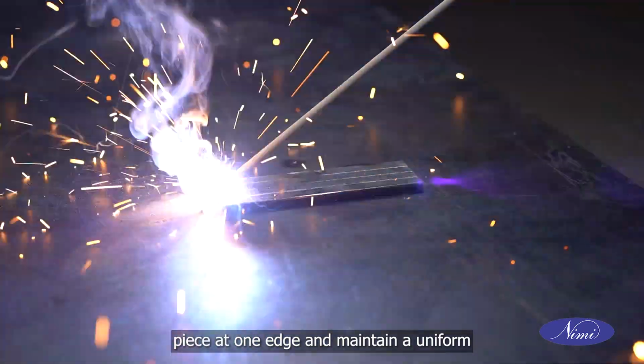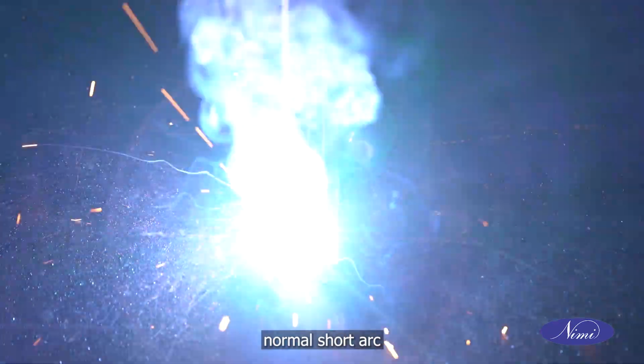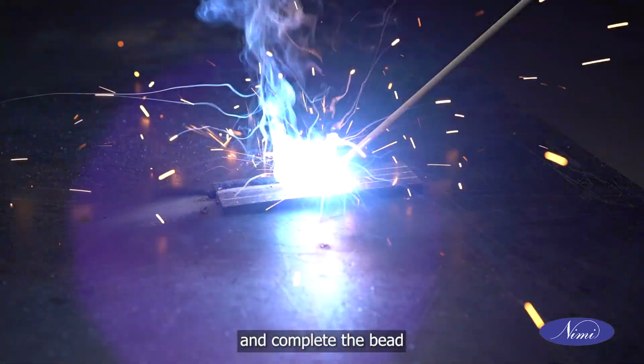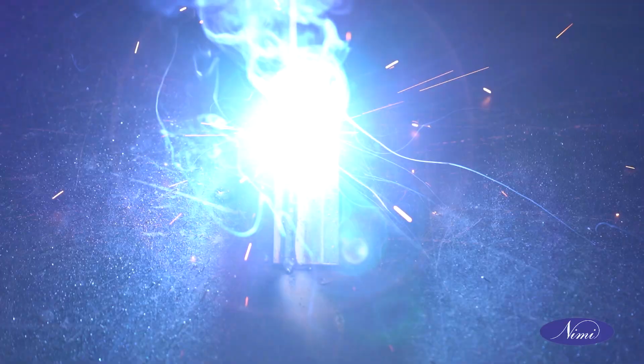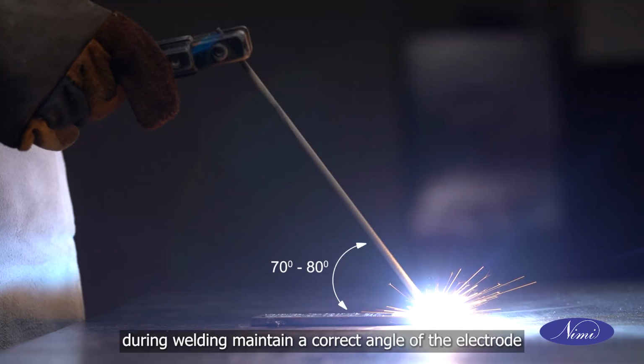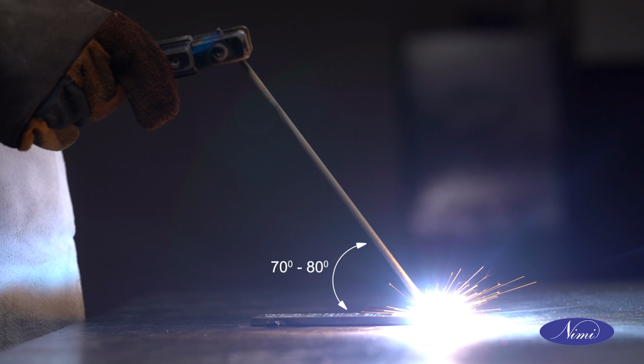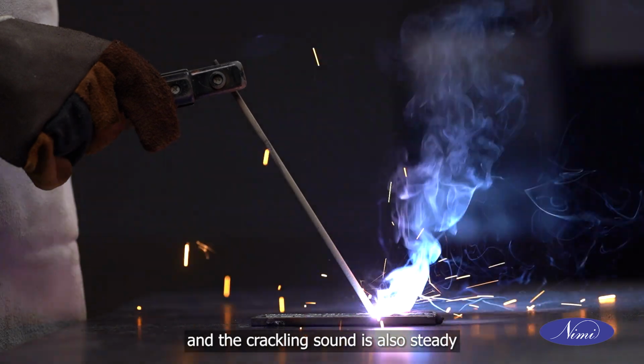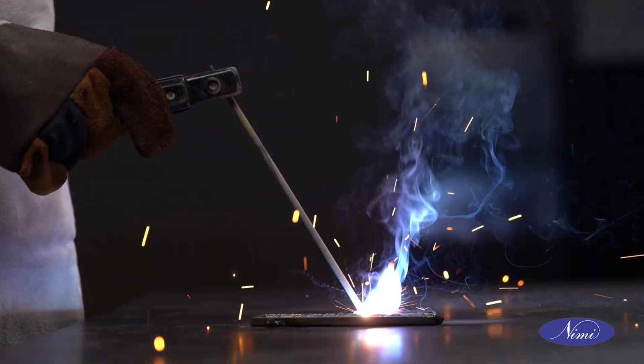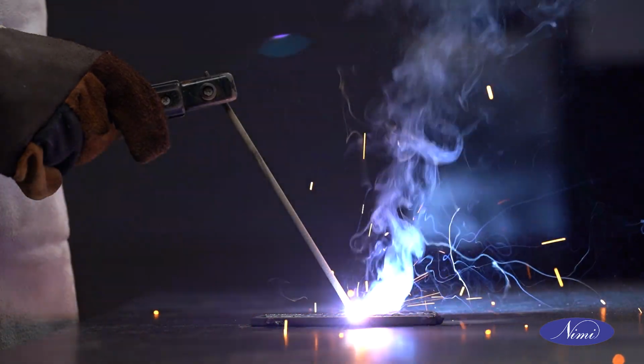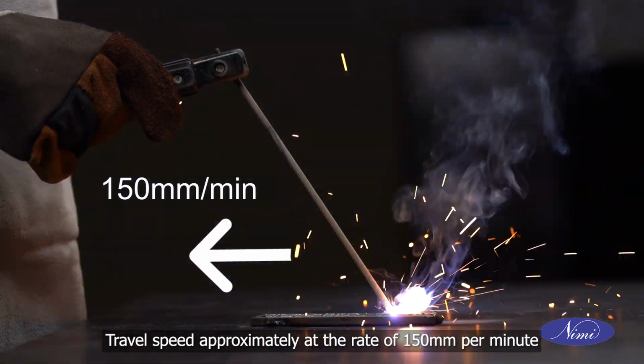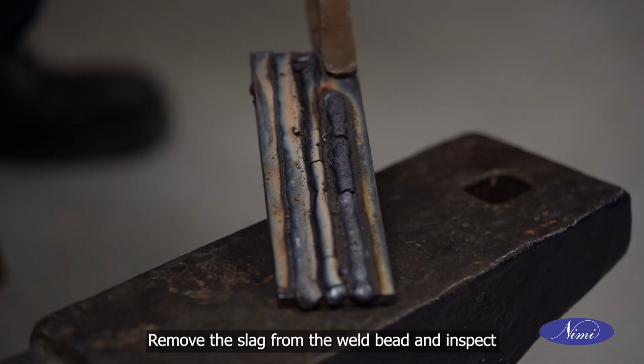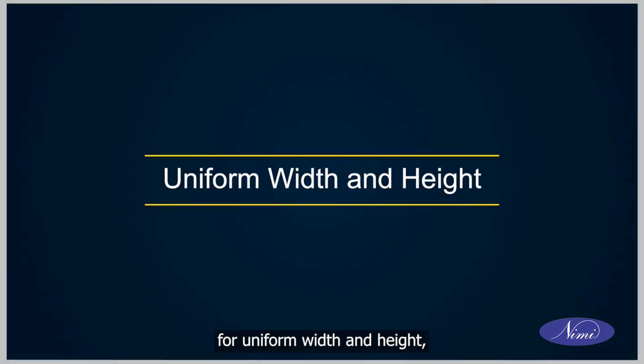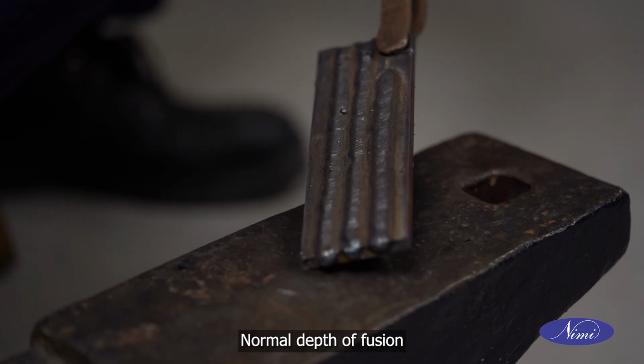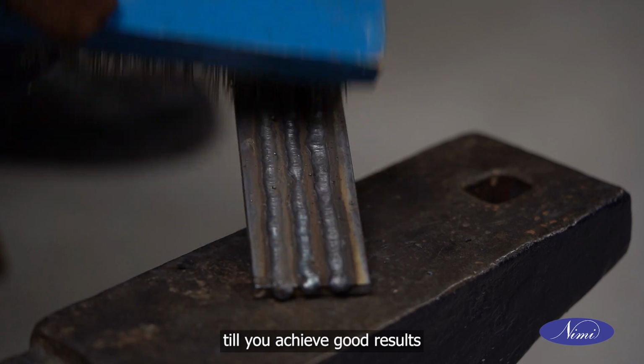Strike the arc on the job piece at one edge and maintain a uniform normal short arc. Move the electrode in a straight line and complete the bead at the other edge of the plate. During welding, maintain a correct angle of the electrode at 70 to 80 degrees. Maintain proper arc length so that the arc is steady and the crackling sound is also steady. Travel speed approximately at the rate of 150 mm per minute. Remove the slag from the weld bead and inspect for uniform width and height, slag inclusion, normal depth of fusion, straightness. Repeat the exercise till you achieve good results.